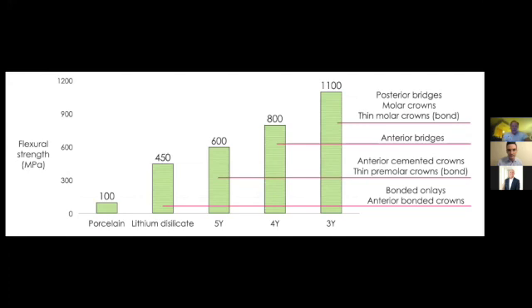Yeah, let me just add a little to this, because what we see in the laboratory is, we look at strengths, and you did address it, but again, this is where I think our ceramists can really help us out, because we got these strengths, but what we see is things are under prepped. So we'll get a premolar crown with an Emax, or a first molar that they want Emax, and they've only got 1 millimeter of occlusal reduction. And that's where I think when we go to a 5Y, and I tell people that, I could show you a 5Y crown and an Emax, and you could hold it up to the light, you could bite on it, you could play with it.